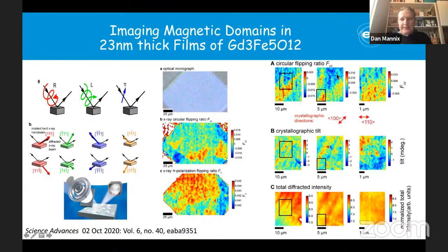What is the nice thing about this, and this is the unique thing really of what we've done here, is being able to correlate, with the same data set, magnetic information and charge or structural information together to see how they interact. Things like strain and defects may eventually affect the magnetic contrast or the magnetic texture. So this is one way in which you can compare the two using the same data set. That's a very powerful probe of magnetism, and it's different, for example, than something like PEEM or other probes that you can use to probe magnetic materials.